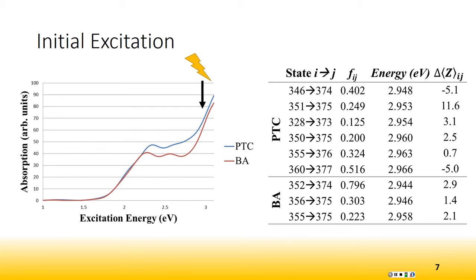So in the experiment, they excite at 2.95 electron volts. And if we look at the states that are important around that region, we can already see the difference. For the PTC, we have some states that are very charge transfer in nature, which would mean that we already broke our exciton into the electron and hole, so then the hole can be extracted very easily. But for the BA, none of the states are that charge transfer.